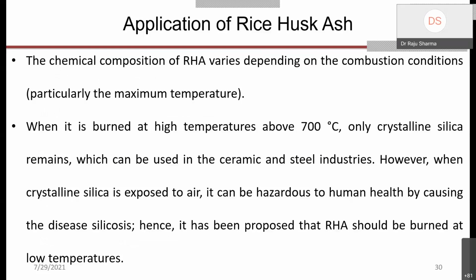We haven't seen this particular thing; we will see it in the coming slides. I will discuss this. So I'm focusing on how combustion affects it. We saw this in the form of XRD, the phases. When it is burned at high temperature, above 700 degrees Celsius, only crystalline silica remains. So you have seen the peaks at 700 degrees in the XRD of the bagasse ash also. You have seen that more crystalline phases are there.